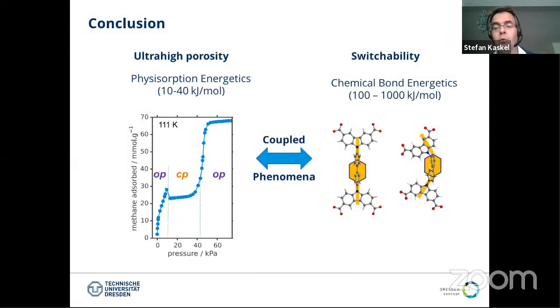Also, as a conclusion, why these two topics are related, ultra-high porosity and switchability, more a global view. So physisorption energies are normally quite small, 10 to 40 kilojoule per mole. And that's the definition of physisorption. And this is not so different in ultra-high porosity materials. But because the magnitude of adsorption is so huge, 60, 70, 80 millimole per gram, when you multiply this, the overall energetics per cell are enormous and they approach chemical bond energetics. And this is the reason why we can start to use physisorption to deform chemical bonds. And the coupling of physisorption phenomena and chemical bonding manipulations, I would say, is from a fundamental point of view, interesting, at least in my view.